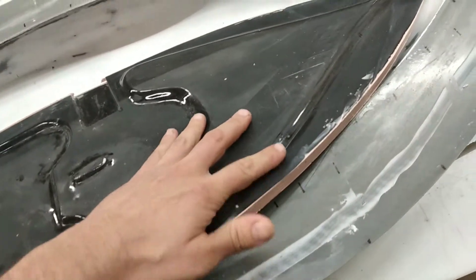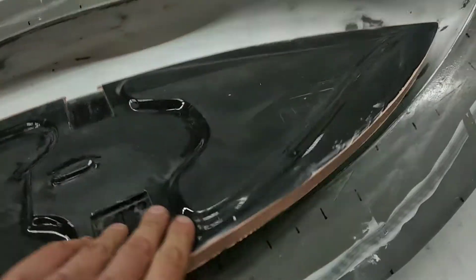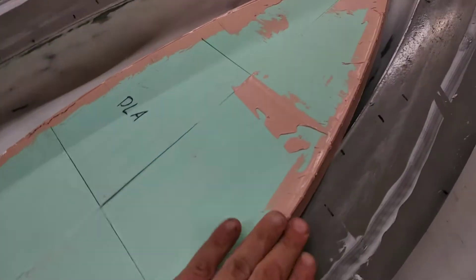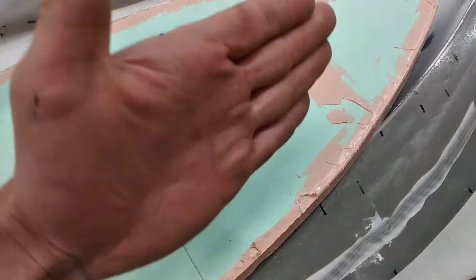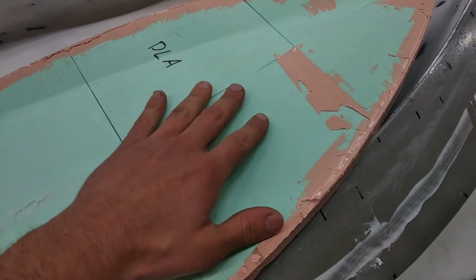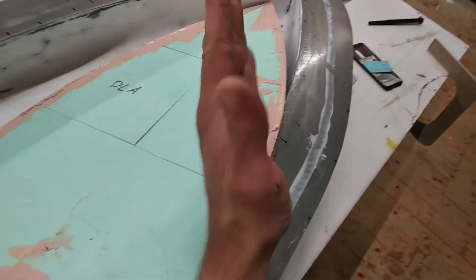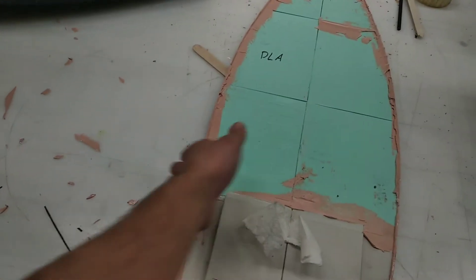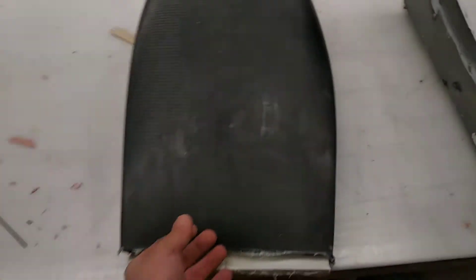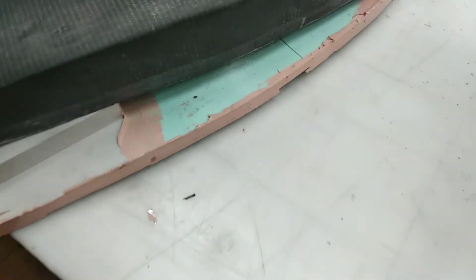This finish is later on sanded back and will be the gluing flange for the whole deck structure to the hull. Mold making will be as follows: I am going to reapply the wood to extend around about here, then make the mold for the top part, then flip everything around and de-mold the wood and build a second layup over here. In case of building the deck I can laminate straight down all around the deck, vacuum bag it, and then de-mold the flange area and have a nice flange looking to the inside of the deck.